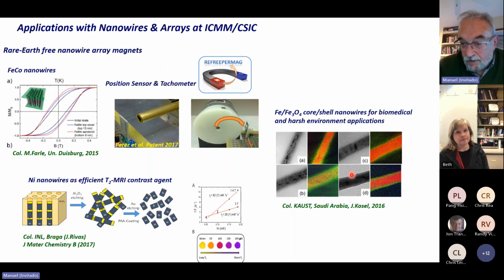Also, in collaboration with other people in Saudi Arabia, at KAUST, with Jürgen Kosel, we were able to prepare core-shell nanowires, iron magnetite core-shell, for some applications. Or in collaboration with the Institute of Nanotechnology in the north of Portugal, in Braga, we were able to prepare nickel segments, starting with multi-segmented nickel-gold nanowires.